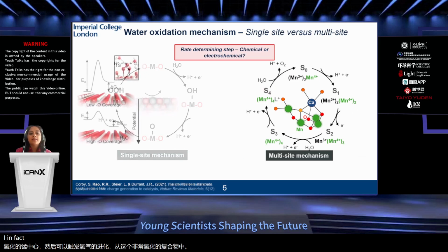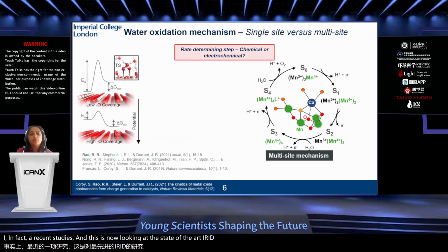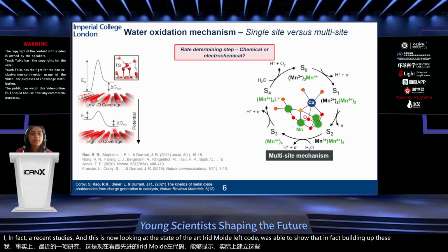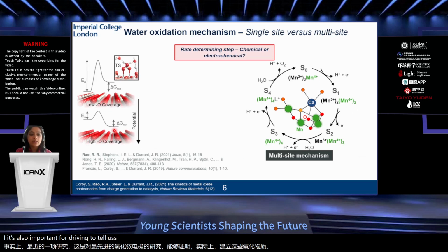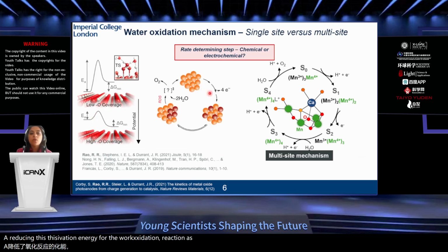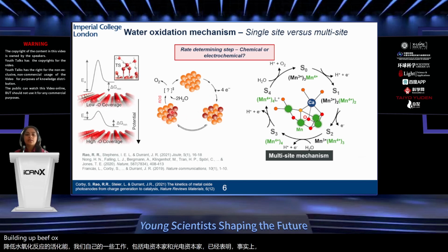And in fact, recent studies, and this is now looking at a state-of-the-art iridium oxide electrode, were able to show that building up these oxidized species is also important for driving catalysis on some of the inorganic electrocatalysts, kind of mimicking this mechanism from photosystem 2. So the idea here is that as you oxidize the surface, you start reducing this activation energy for the water oxidation reaction. Now, some of our own work, both electro and photoelectrocatalysts, has shown that building up these oxidized species is important to be able to trigger this rate determining step of OO bond formation for water oxidation. But it's still quite unclear how the actual kinetics of this reaction take place.